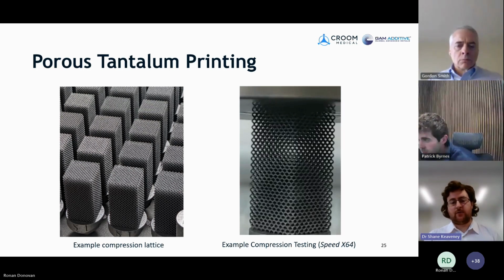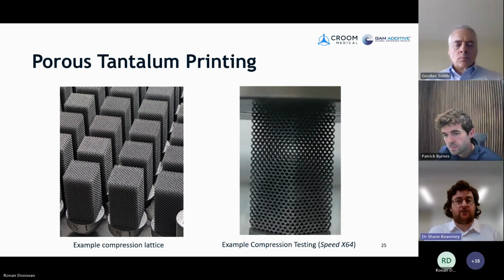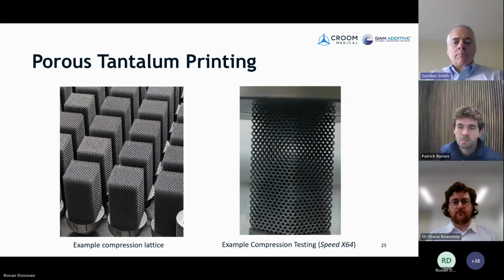So if, for instance, there was some large strain on this implant after implantation or during implantation with the tantalum, we're less likely to see a failure or a breaking off of any of the struts. So that's a big advantage.